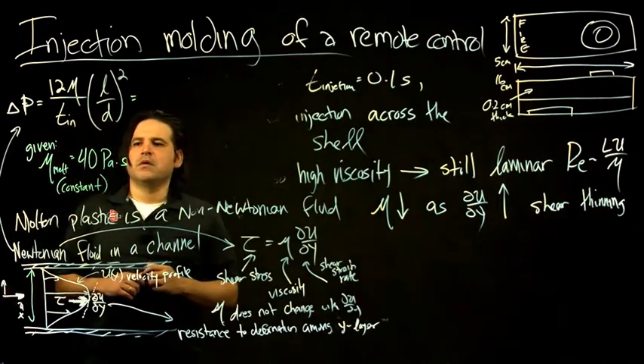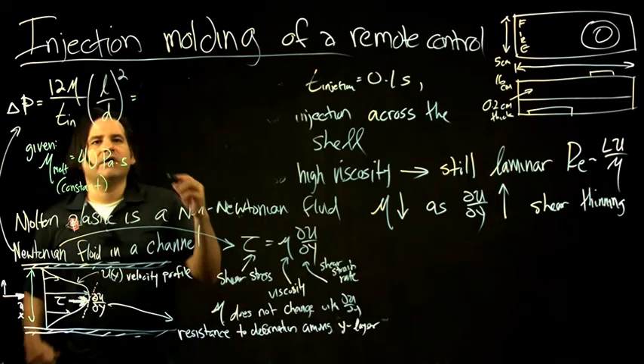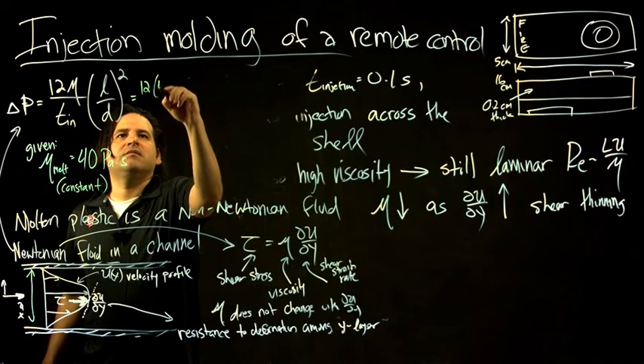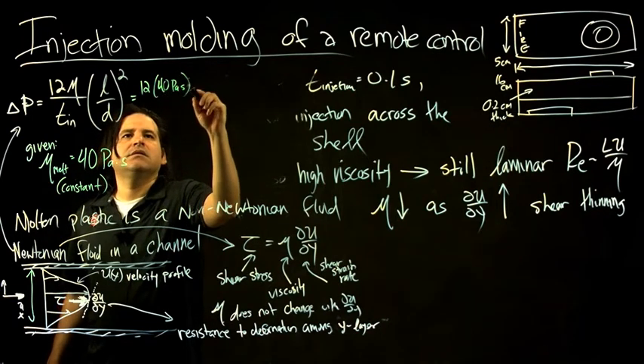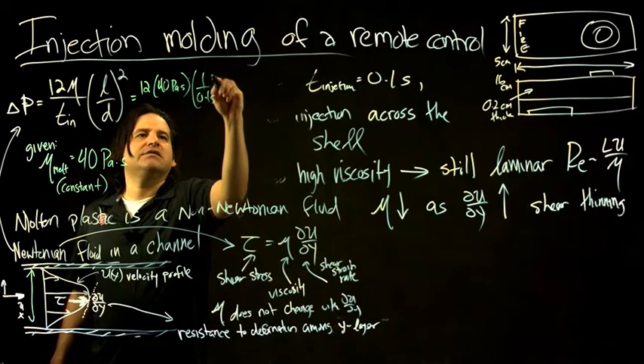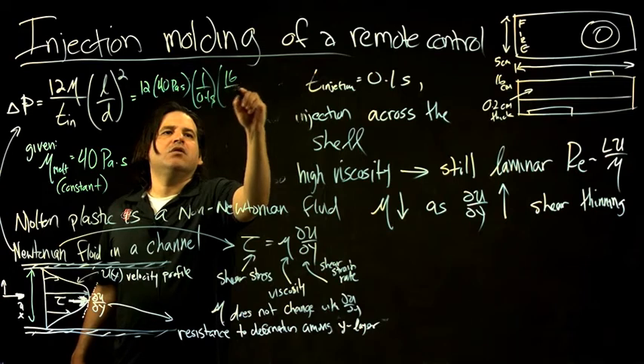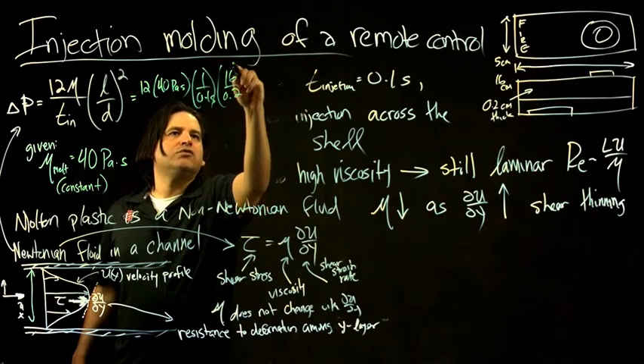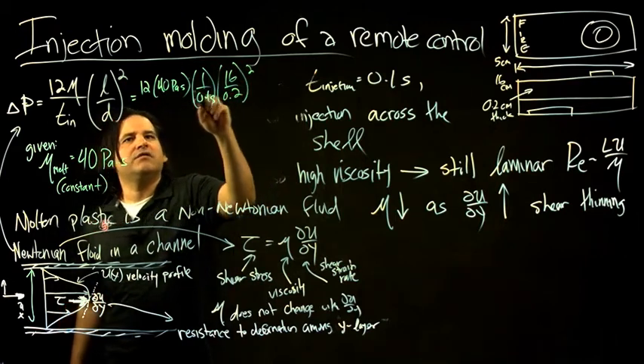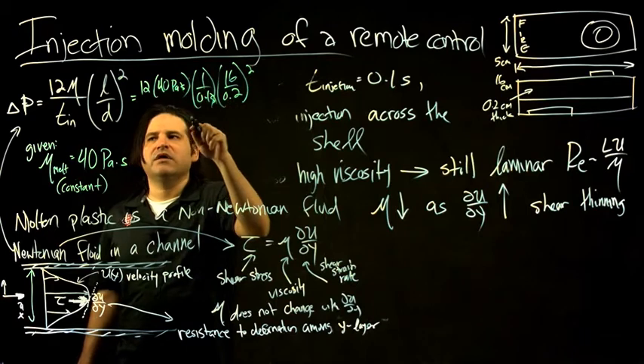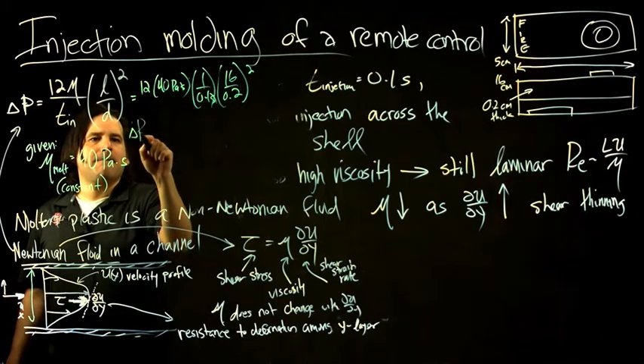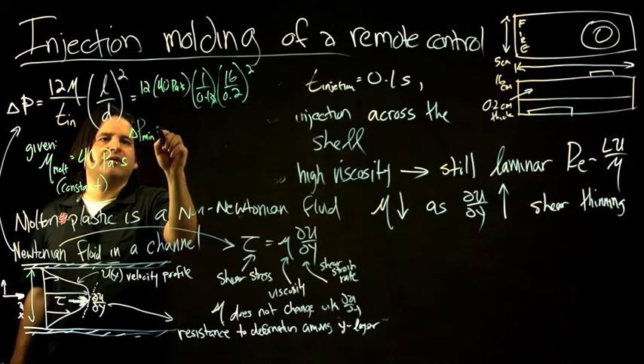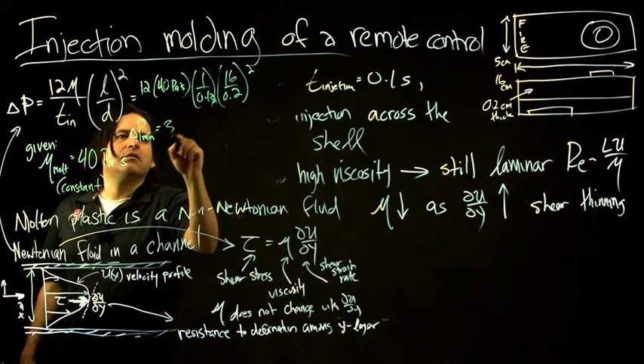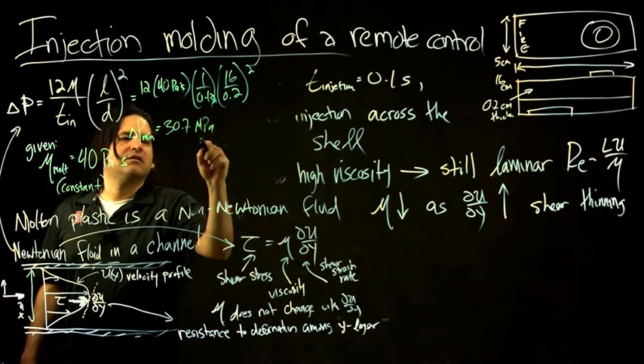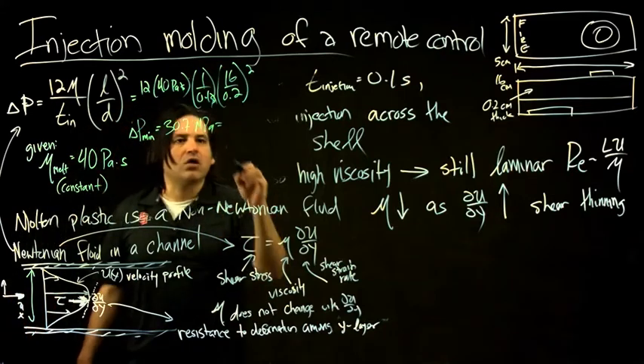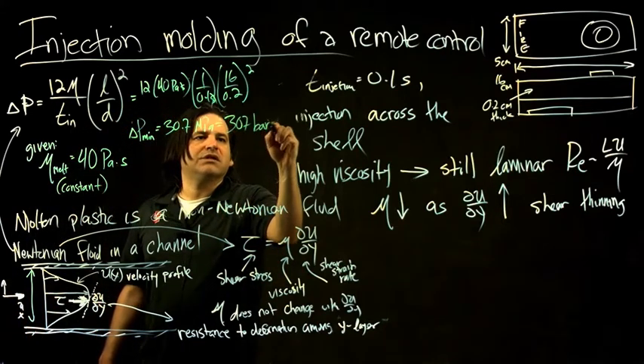Okay, so let's plug that in. What we'll get is 12 times 40 Pascal seconds times 1 over 0.1 seconds times 16 over 0.2 squared. These are both centimeters. So that gives you a pressure drop in Pascals. The seconds canceled out. So delta P minimum, we'll talk about why it's minimum, is 30.7 megapascals, equals 307 bars, which is a lot.